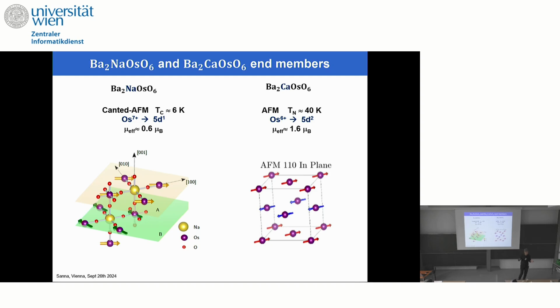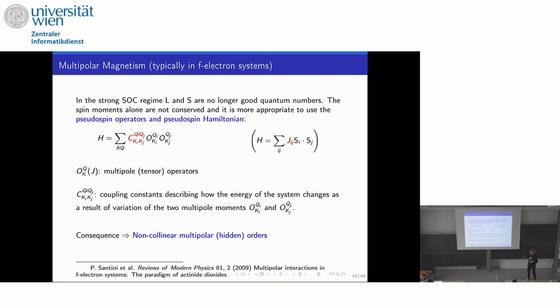No, probably not, but probably the first end member, the sodium, is now a good description of what is going on. And we know the magnetic structure. And for the calcium compound, the former interpretation was a standard antiferromagnet, but now we know that we also have to consider the multipolar character of these materials. And so, starting from this very famous paper from the group of Santini and Moretti in Parma, which was mainly dedicated to actinides, they started introducing these multipolar interactions in heavy elements.